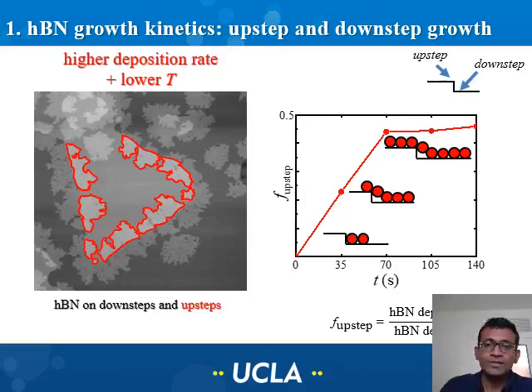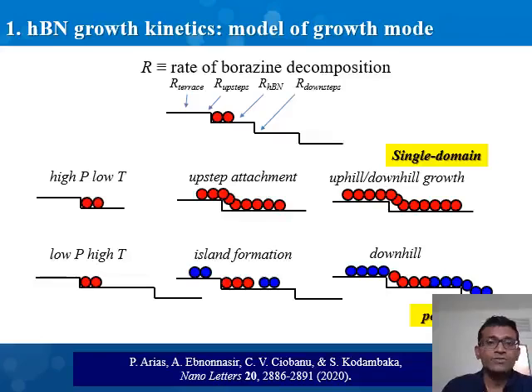And here is a schematic illustration of what we think is happening during this process. Initially, during the initial stages of deposition, attachment occurs primarily at the down steps. With increasing time, there is an extension of the already deposited layer towards the up steps. So without going into additional details, I'm going to summarize what we think is happening. And here is the